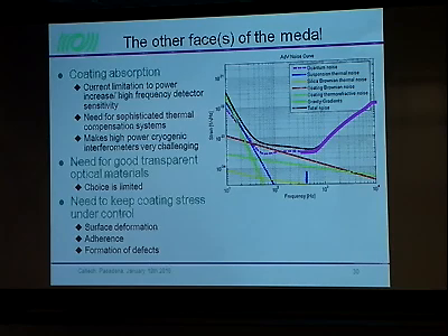In particular, the stress in the coating can play a role on the overall performance because it can deform the surface of the mirror. It can play a role in the adherence of the coating on the substrate, and it can be a source of formation of defects inside the coating. So all these parameters have to be taken into account.